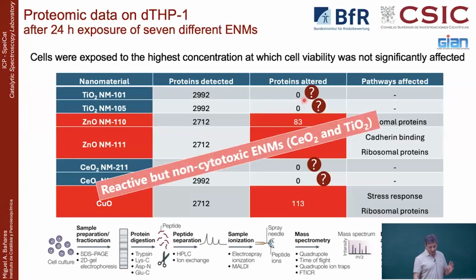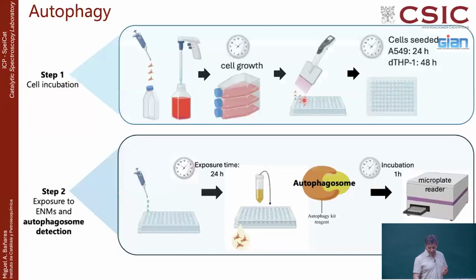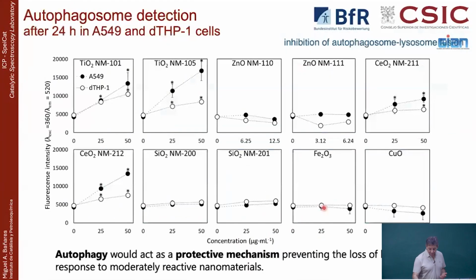So that was strange, because an inert material is okay, and a reactive material is killing and doing damage, okay. But moderately reactive materials were not cytotoxic. We were doing a lot of assays to measure whether autophagy is triggered, so they can detect the generation of the autophagosome. And a long story short, for the reactive materials, you don't get any autophagosome triggered, but that is because the cells are dying, so they don't have a chance to do anything.